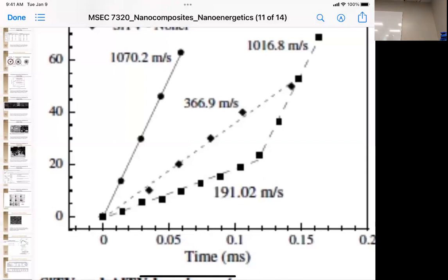The gradual entry, actually, this is bad because it has two slopes, a slow and a fast. That's going to get you starting to burn, then you'll have a whole bunch of it, then it'll all change burn rate, and that's a bad thing in a propellant. You don't want to do that. It's not a bad thing in a warhead, but it's a bad thing in a propellant. You don't want it to change rates. That broken line is a bad thing.